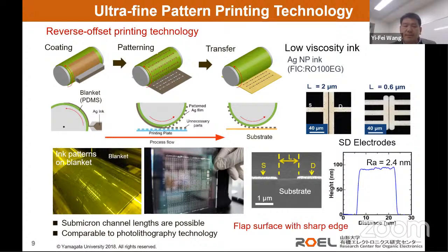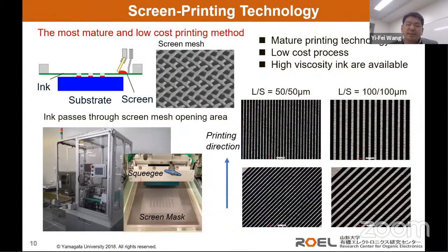And also, this method can very easily fabricate highly integrated circuits. Another advantage for this method is we can fabricate the electrode film with quite a flat surface and also very sharp edge. This is the reverse offset printing, and then we also have another printing method which we call screen printing. It's the most mature and low cost printing method.